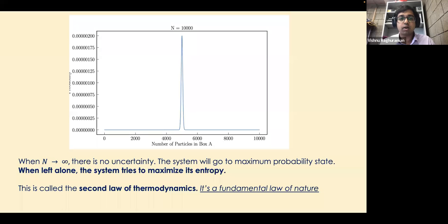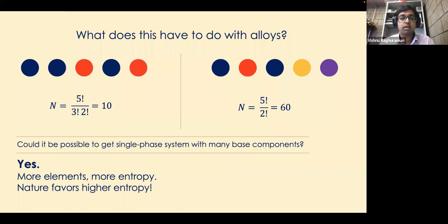And what does all of this have to do with alloys? So if you have more elements, there are more ways to arrange your system. So since there are more arrangements, there's a higher entropy, which means the system will try to go to a higher entropy state. And since a higher entropy state is favored, it means that you could get a single phase system with many base components. You wouldn't have a clumping of different phases everywhere. You would have a uniform mix because more arrangements are associated with that type of mix.